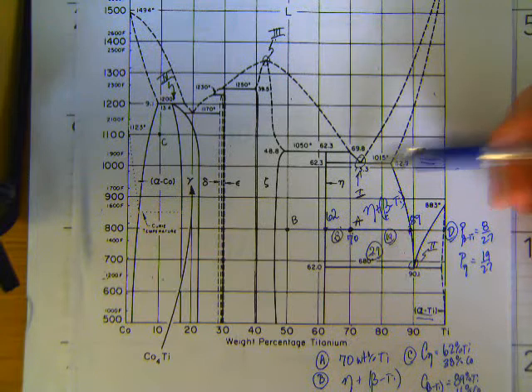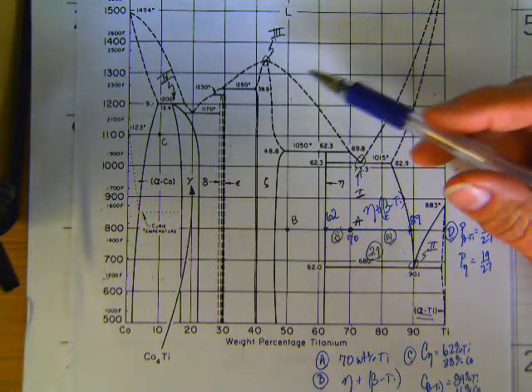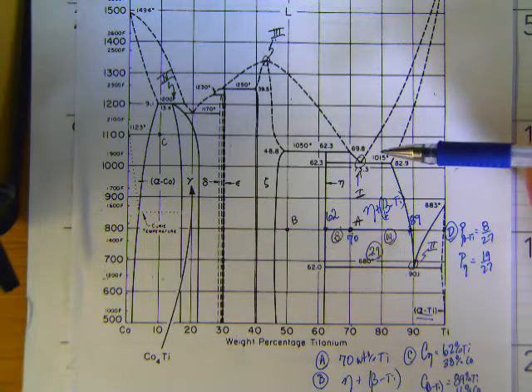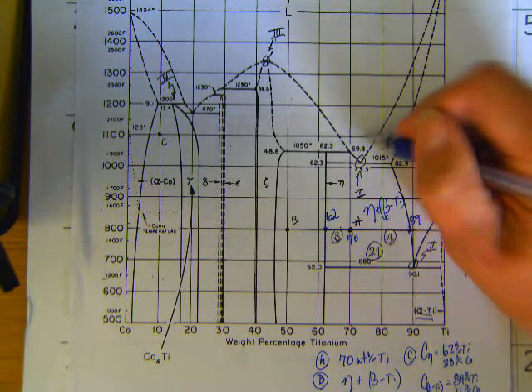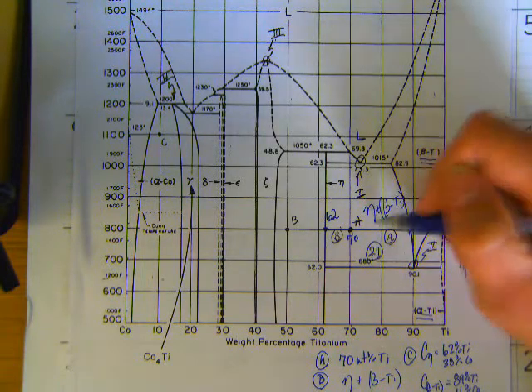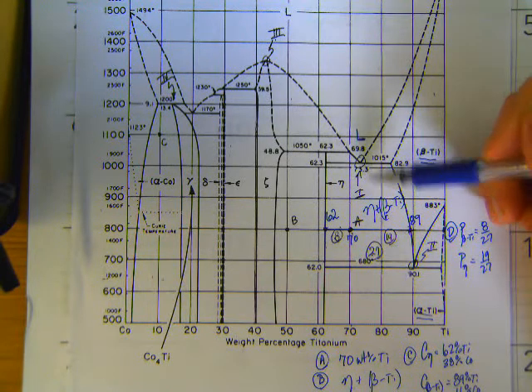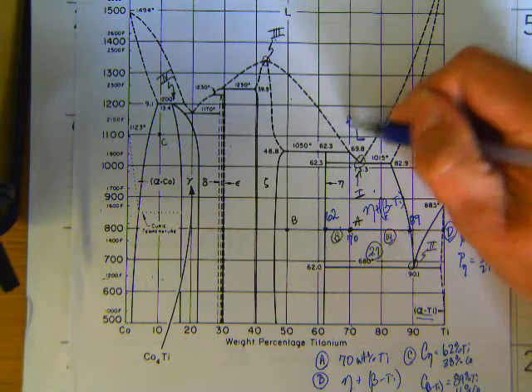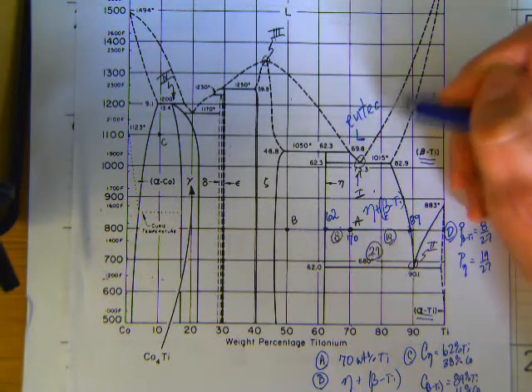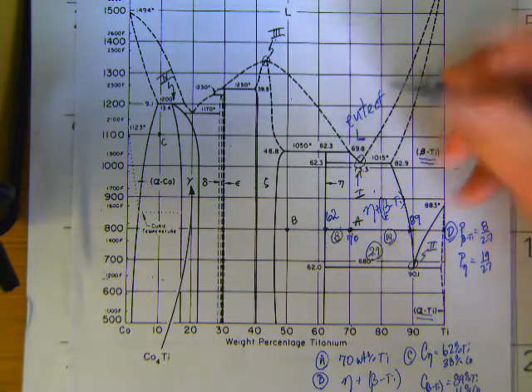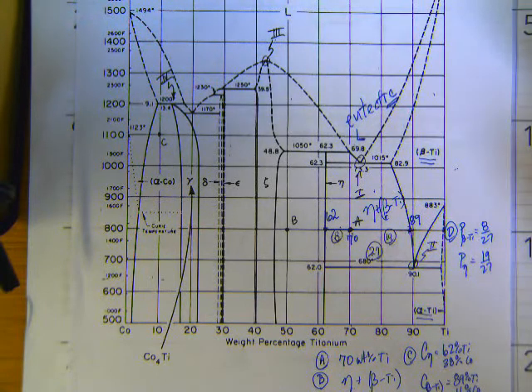A couple of other interesting points that maybe we want to take a look at here. There's several points that are potentially invariants. It's not that they all are, but a couple of them that are worth looking at. Remember, for invariants, we're talking about a point at which three phases exist in equilibrium, three different phases. And so the first point would be this that's labeled I. And up above, we have the liquid phase, the molten material. And down below, we have these two phases we've just talked about. So I have a single phase above turning into two phases below. Since the single phase is on top, this makes a V. That looks a lot like the V in a eutectic. And then the question is, what is this? What are the systems? Does this involve liquid or is it all solids? And obviously we have a liquid involved. So that's a eutectic system. Liquids are icky and sticky. And that's going to end in eutectic.